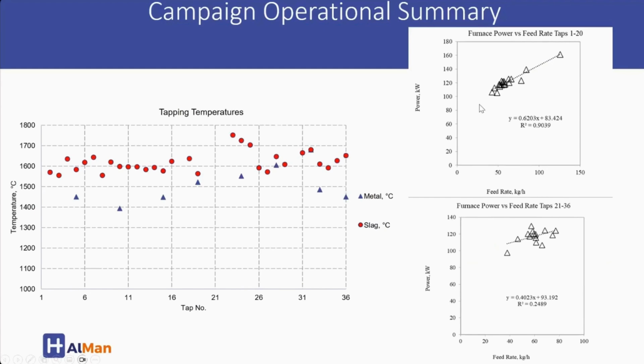These are results from the actual test work. Remember the preliminary simulation gives you an indication of your SCR based on the conditions you input, but during the test work, you can also do a calculation or measurement of your SCR. So the SCR is given by the coefficient of X in this linear equation, and as you can see, for smelting of slag, the SCR is 0.6.